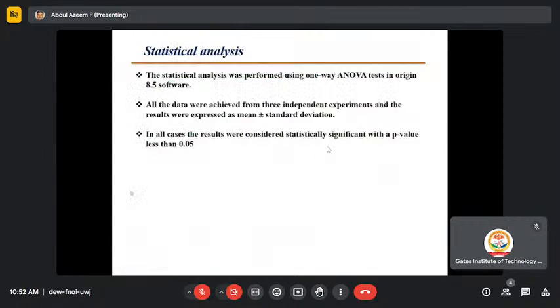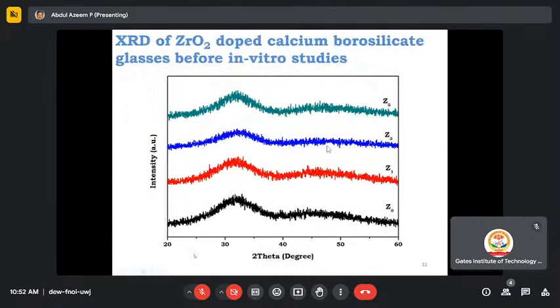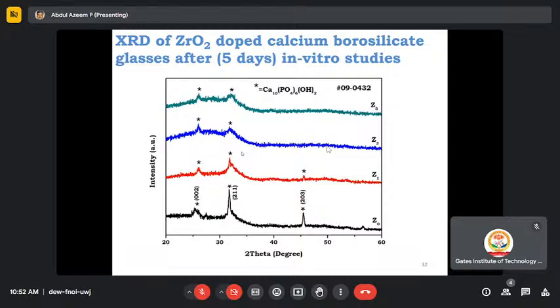I'll show you. So this is regarding the glass. This is the XRD of the glass. You don't have any sharp peak. It confirms that the material you prepared is glass in nature. This is before immersion, when you prepare the glass and check it. Now, after immersion of your material into the simulated body fluid for 1 hour, 1 day, 1 week, or 5 days, or 21 days, whatever it may be.